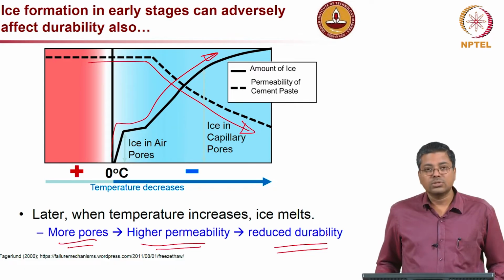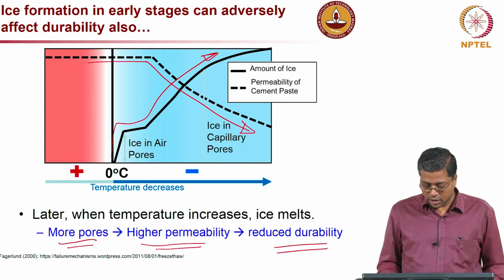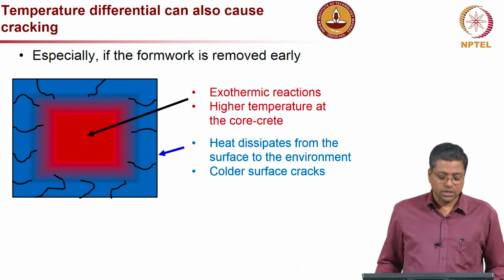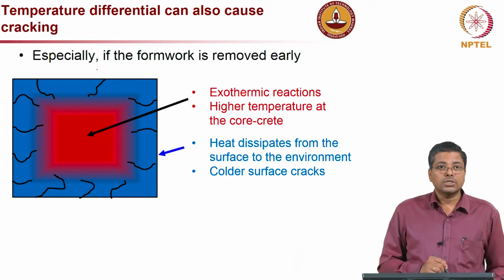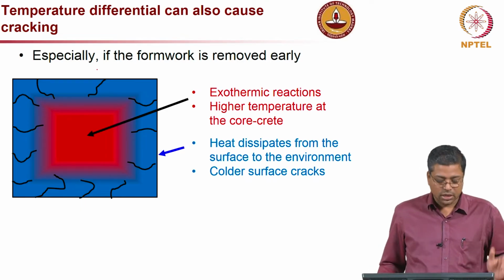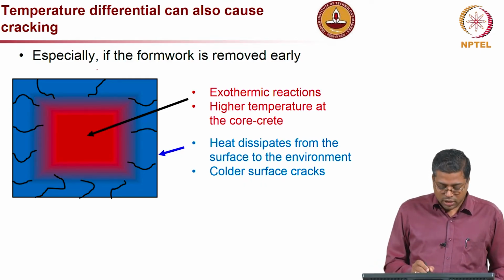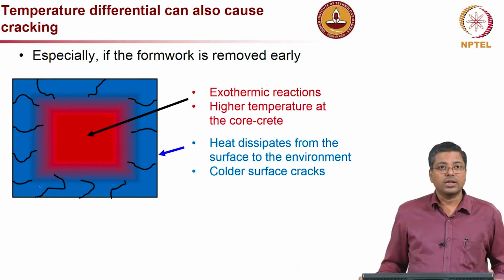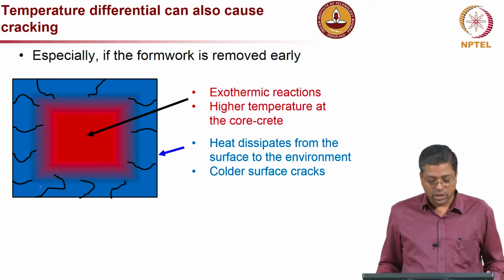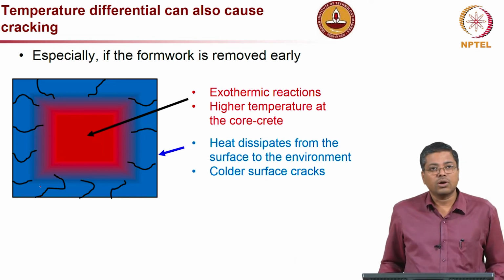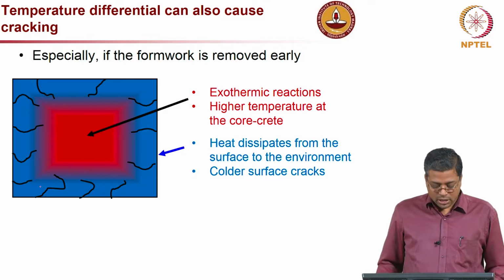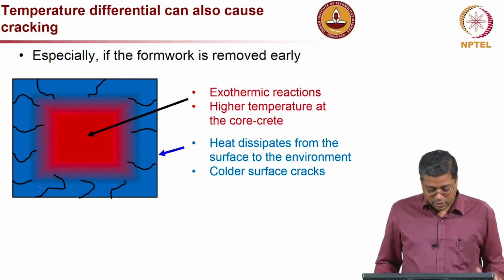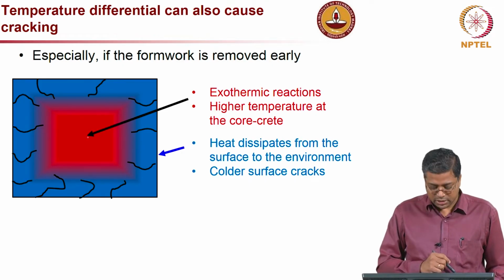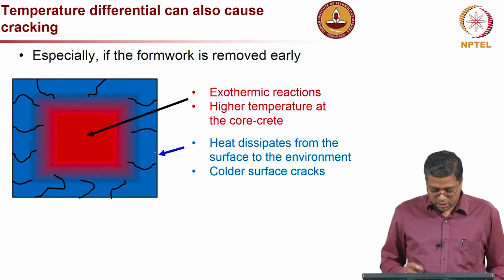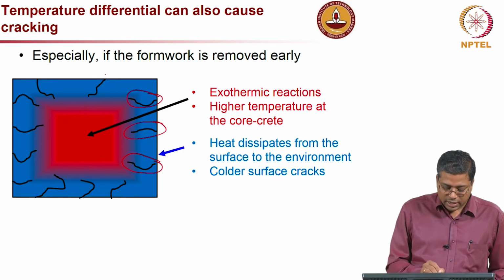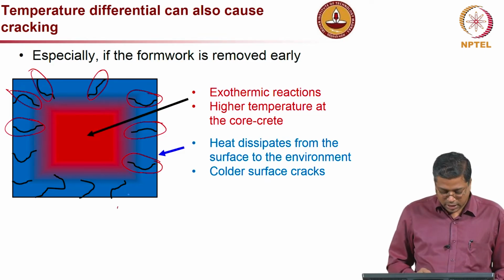So, this frost attack is also very important to consider, not only for strength, but also for durability. Now, the other effect is the temperature differential induced effect. You can see here this is a schematic showing a mass concrete. Imagine this is a cross section of a concrete column, and when the formwork is removed, the heat generated in this blue or peripheral region is lost into the immediate environment, which is actually cold. But at the same time at the core of the concrete you will still have a reasonably high amount of heat. So, there is a temperature difference, or thermal differential, between the core and the peripheral region of the concrete, and because of this differential temperature the concrete will experience significant cracking near the peripheral region. All these black areas indicate the cracked region.